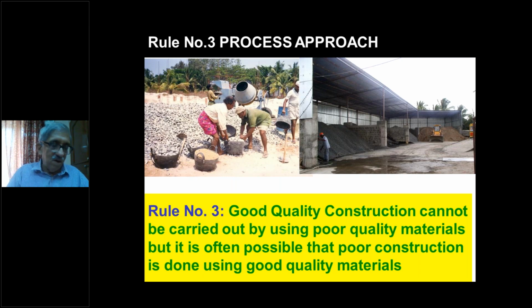And it's only where the ready mix companies come in, the quality has improved, and that also it is improved if it is properly supervised. On the left hand side, you can see the manual way of M-20 concrete being done. You can distinctly see that the aggregates are of a very large size, cannot be 20 size, but they are almost the size of the potatoes and onions they get in the market, which is not fair to the concrete. And the sand is very fine. So, of course, you will never get dense concrete. You will always get gap graded concrete, which may be very easily segregating and causing honeycombs, etc.